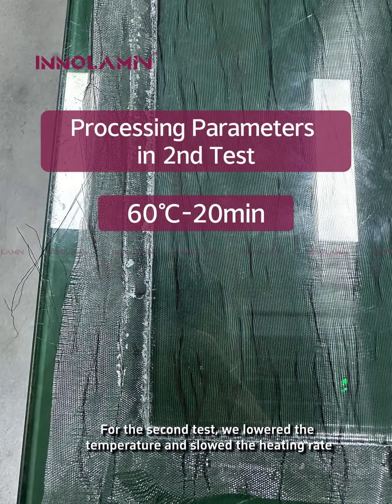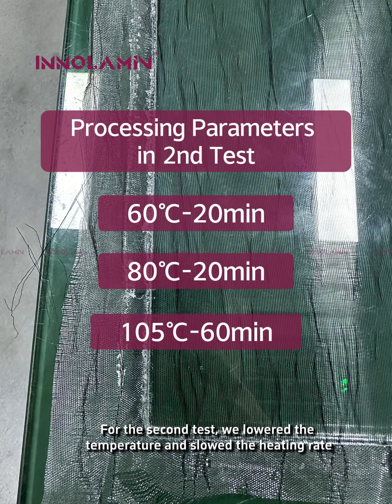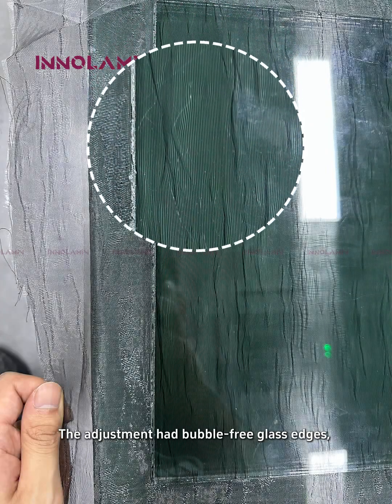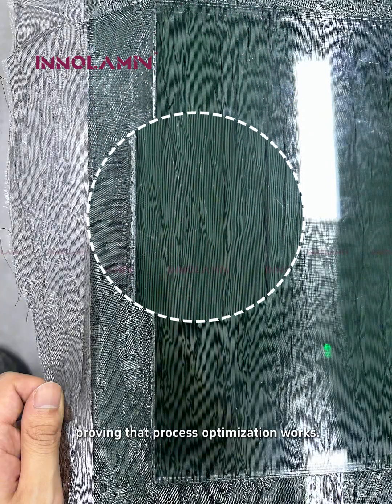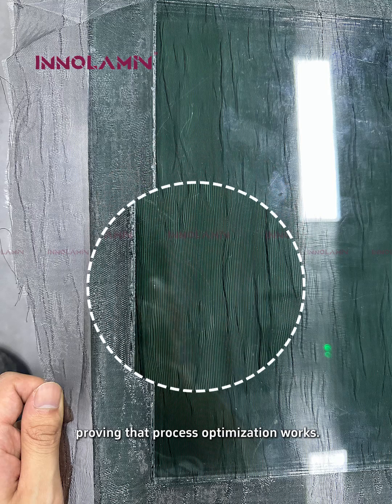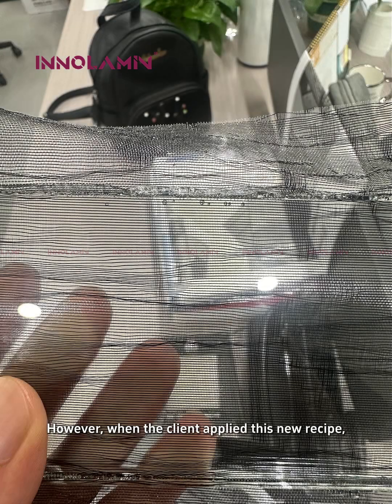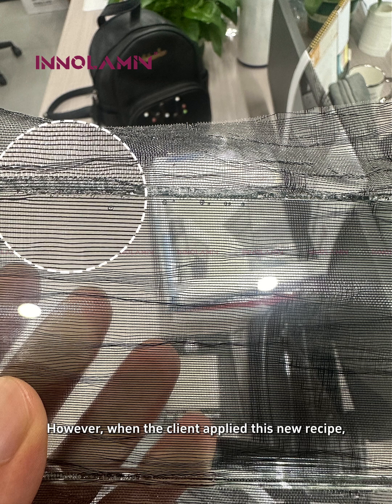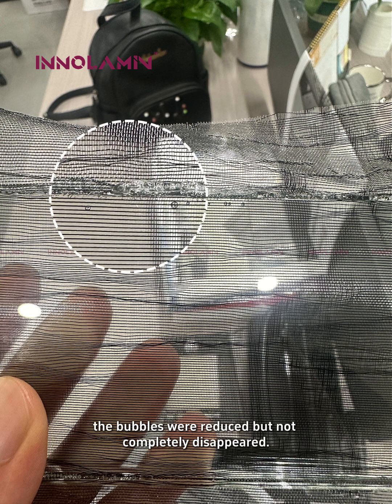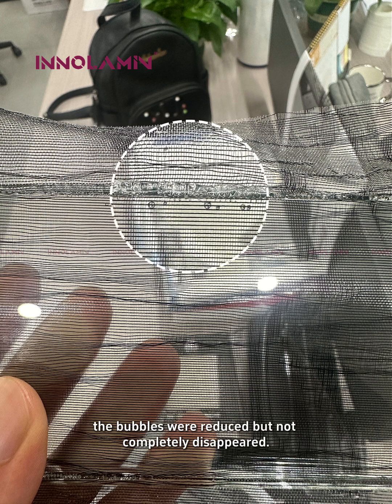For the second test, we lowered the temperature and slowed the heating rate. The adjustment produced bubble-free glass edges, proving that process optimization works. However, when the client applied this new recipe, the bubbles were reduced but did not completely disappear.